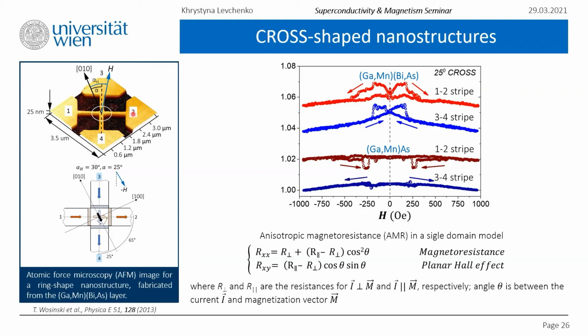Let us interpret that. So again, like in the nanoring, because we fabricate the stripes so narrow, we are forcing, because of the strain, the spins of these segments to be aligned along them. So in the stripe 3, 4, for example, this, and 1, 2, for example, this. But the middle segment, in contrast to the previous design, is unconstrained. There is nothing forcing the spins to be aligned along a specific direction, and we see this nice 360 rotation depending on the application of the magnetic field.